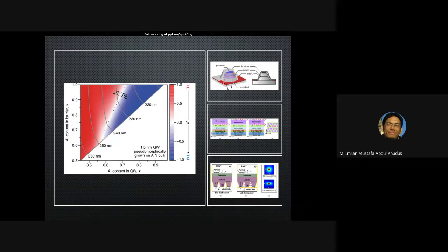Some people have used this kind of strange structure, right? They put aluminium mirrors and magnesium fluoride. Magnesium fluoride is transparent, so that's good, and down to 200, so that's good, right? They've also used different kinds of structures. Normally what they do is roughen the structure up like this, and then do some other stuff, just to improve light extraction. You can see it's not very clear here, and apologies for that, but you have structures here and structures here and in both of them, right?